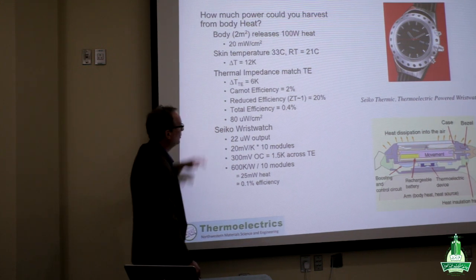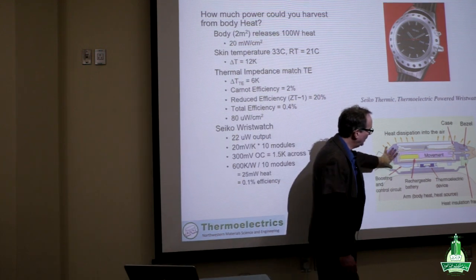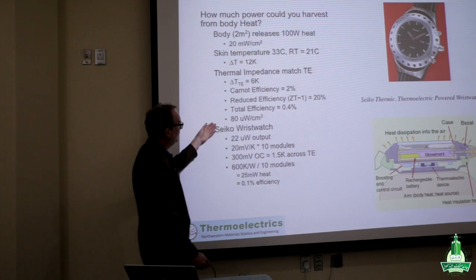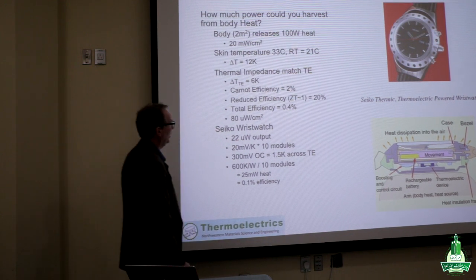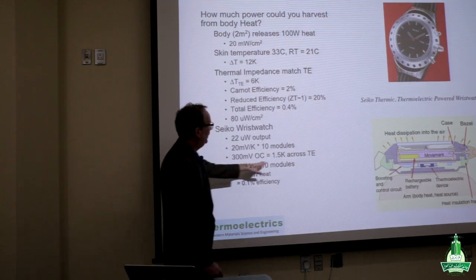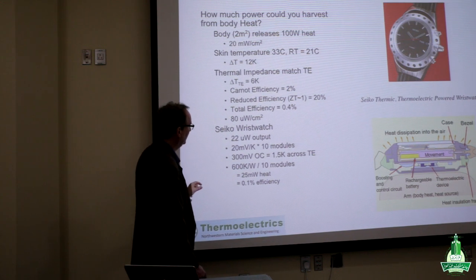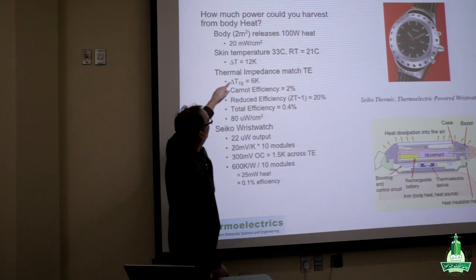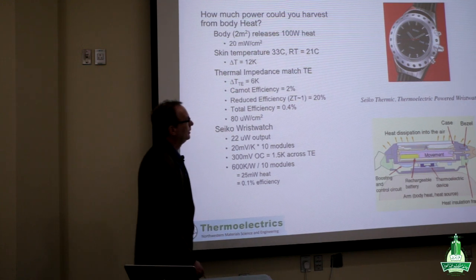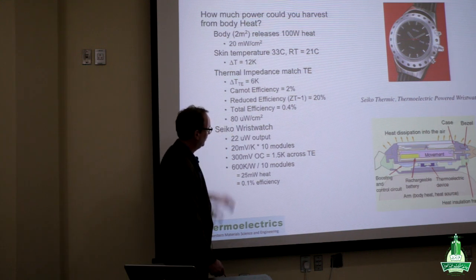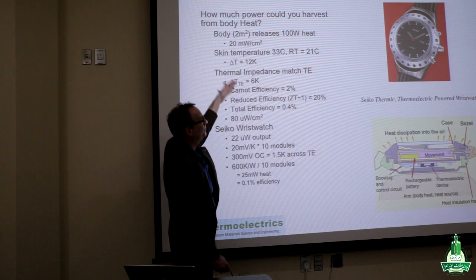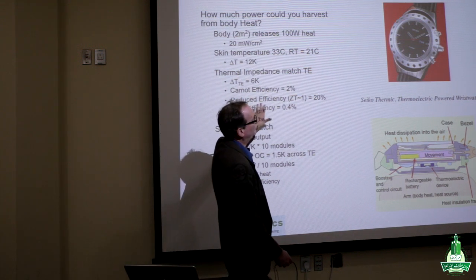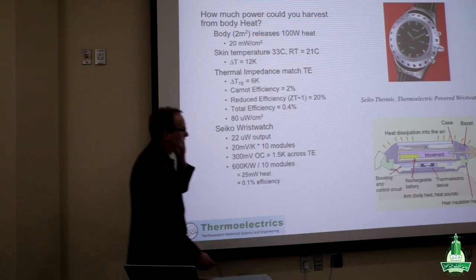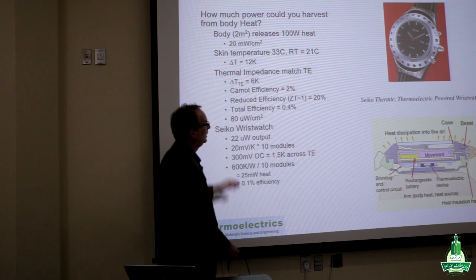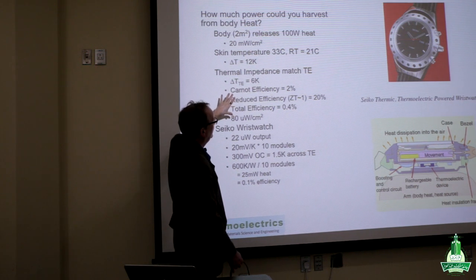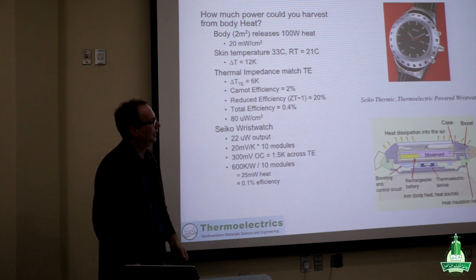So for the Seiko wristwatch that we helped design years ago, they made a module that had about 22 microwatts of output from 10 modules. They had about 1.5 Kelvin across the thermoelectric, which is pretty good, of similar order to what we expected as the maximum power out of the system, 80 microwatts. So this method of approximating the power seems to be reasonable with experiments, and gives us a good estimate of how much power we could expect for a wearable device.